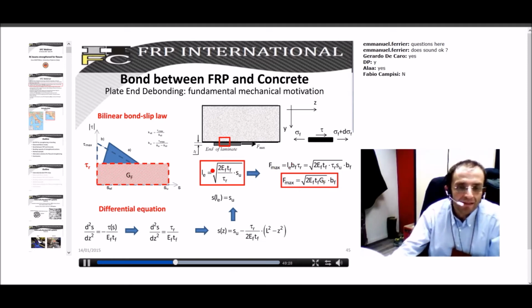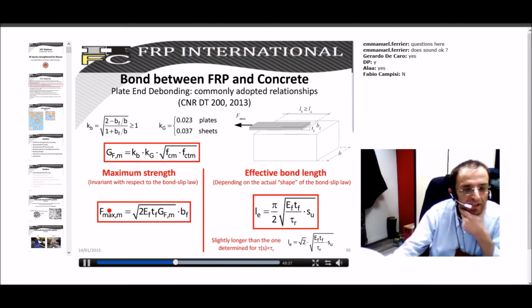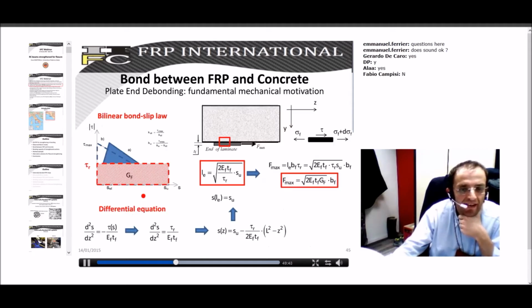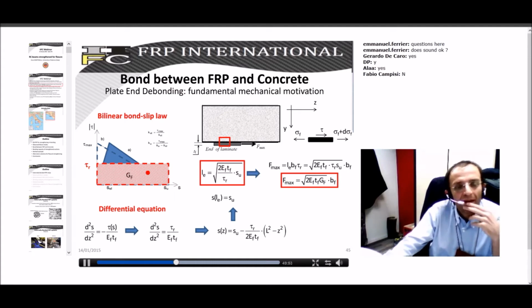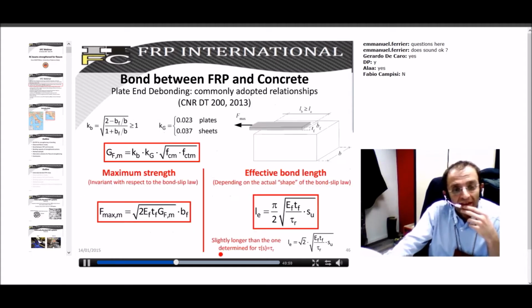It is worth highlighting that these two equations have two different meanings, two different scopes. The expression of the maximum force depends, as you see here, on GF. GF is the area of the tau slip relationship. So GF is the so-called fracture energy, describing the cohesive fracture process. And it is worth highlighting that this formula is valid, can be applied to any tau S relationships characterized by GF.